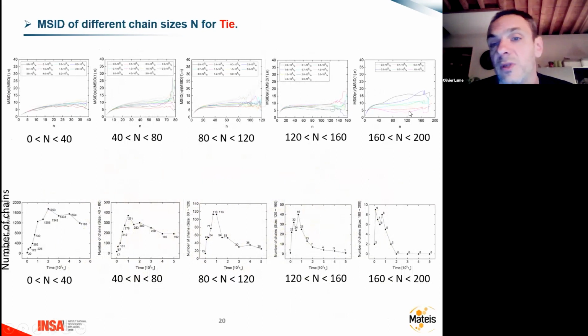And again, it's quite difficult to interpret here because there are some strong fluctuations. So it's difficult to say. Maybe there are some tie molecules which are too taut, and other tie molecules which are very folded. So the average is in the middle. It's not far in average from the equilibrium, but maybe the distribution is very broad. So it's quite difficult to interpret.